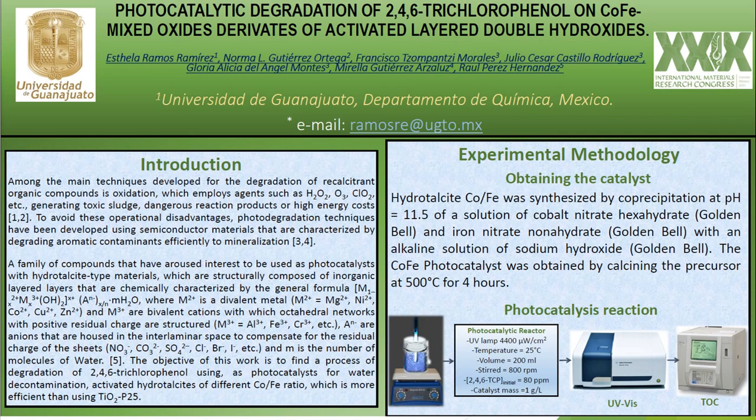are structurally composed of inorganic layers that are chemically characterized by the general formula, where M2+ is a divalent metal and M3+ is a trivalent cation, with which octahedral networks with positive residual charge are structured. A- are anions that are housed in the internal laminar space to compensate for the residual charge of their sheets, and m is the number of molecules of water.